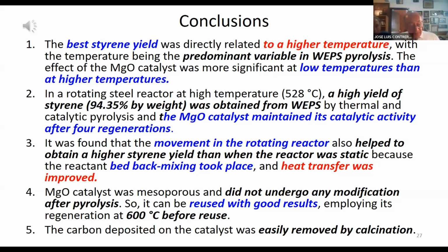It was found that the movement in the rotating reactor also helped to obtain a higher styrene yield than when the reactor was static, because reactant bed back mixing took place and heat transfer was improved. The magnesium oxide catalyst was mesoporous and didn't undergo any modification after pyrolysis. So it can be reused with good results, employing its regeneration at 600 degrees Celsius before reuse. The carbon deposited on the catalyst was easily removed by calcination.